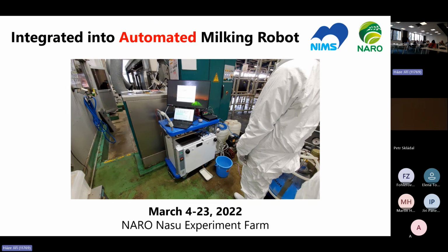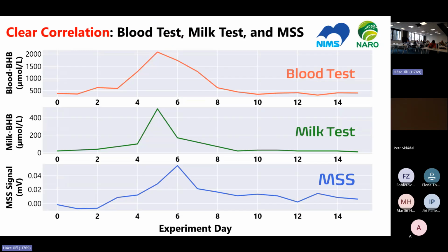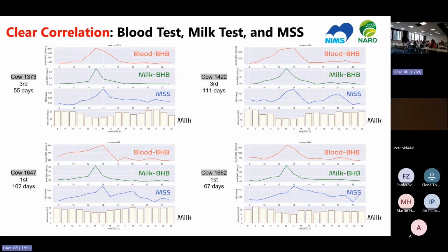So it's a huge system. And we confirmed that even at the farm, we can still measure our signal, and it is consistent with a blood test and a chemical milk test. We confirmed this with all 4 tested cows.